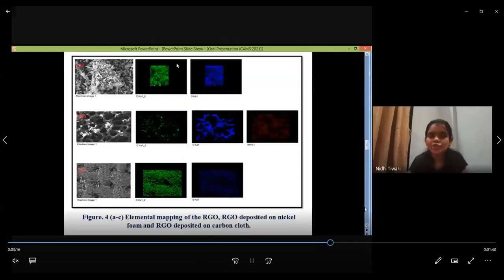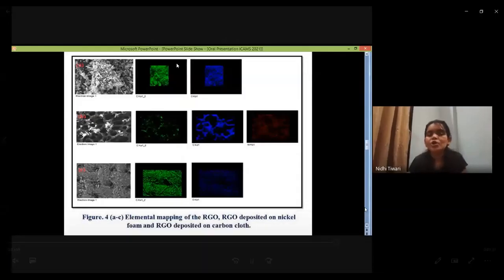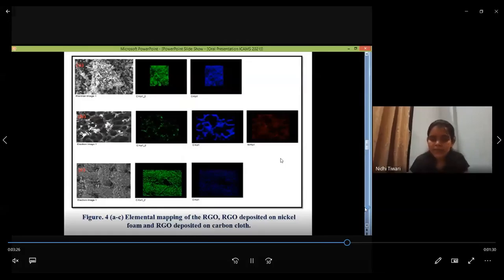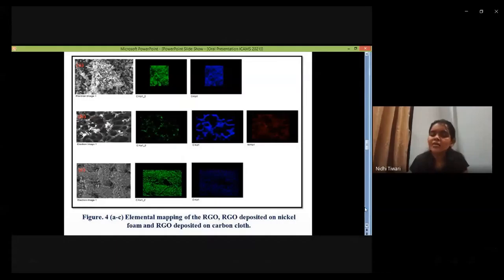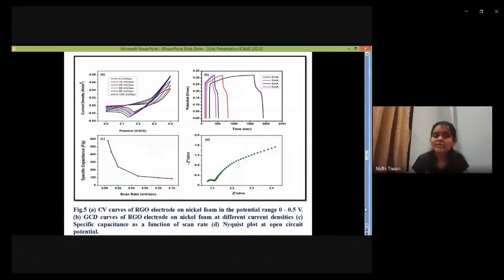So RGO, RGO on nickel foam and RGO on carbon cloth. Green and blue colors show carbon and oxygen respectively, whereas for nickel foam, a reddish color represents the presence of nickel. So elemental mapping and morphological studies reveal that the RGO material has been perfectly deposited and no impurities are present.